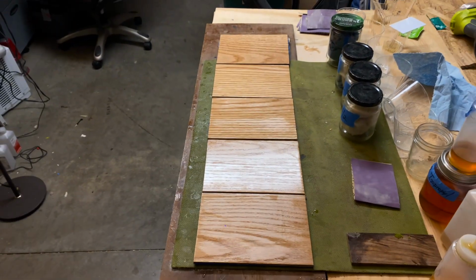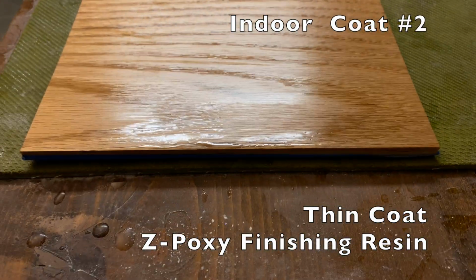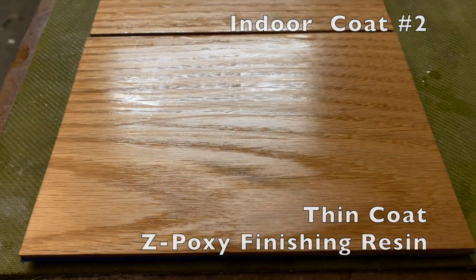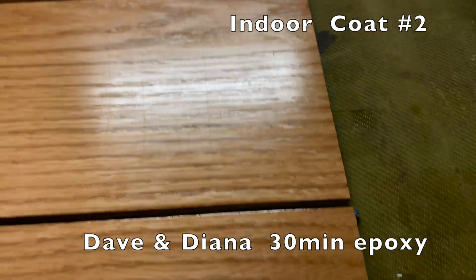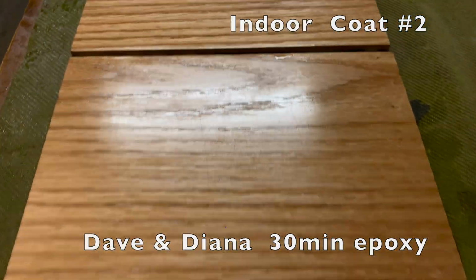Here are the results after letting the second coat dry for 24 hours. It seems to me that these coats applied indoors appear to be a lot thinner than the ones that were applied when I was in the cold garage.